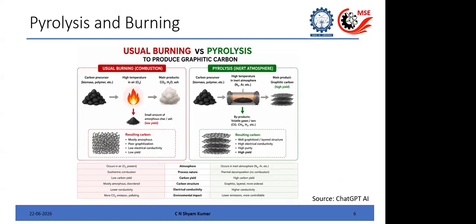So what is this pyrolysis, and what is the difference from normal burning? Because if you burn something, you also make carbon, right? But what is the difference here? Pyrolysis is basically heating without oxygen. So you heat it in an inert atmosphere, or you heat it in vacuum. But when you normally burn it, you make carbon which is mostly amorphous, sp3 hybridized, and the graphitic content, that is sp2 content, is very low. Some of the properties such as electrical conductivity, thermal conductivity, and other things are because of the sp2 nature. So you will lose all those things.